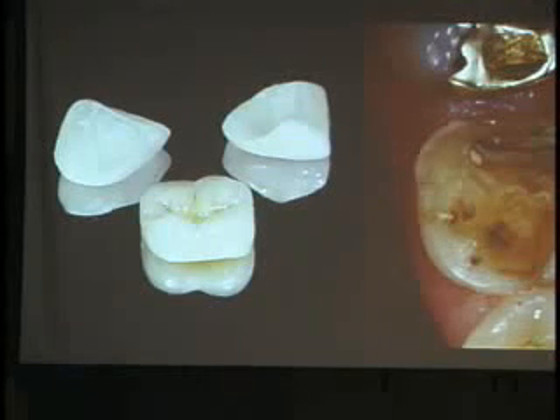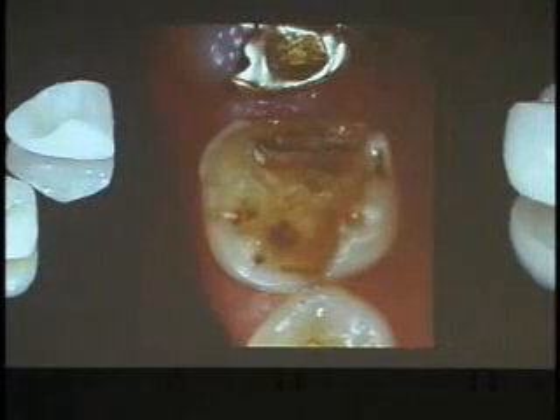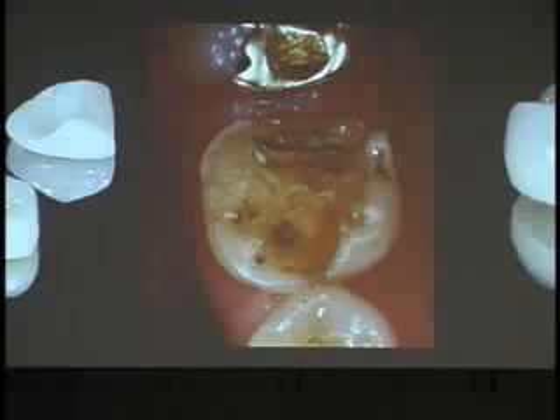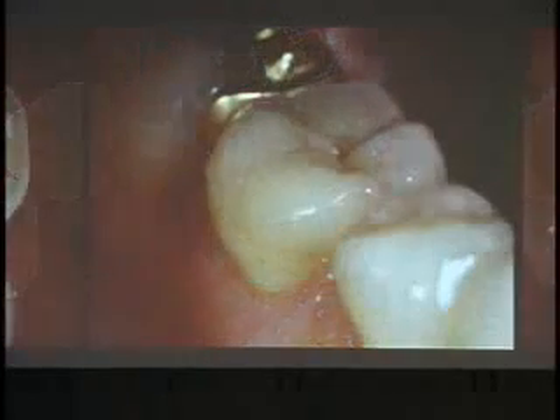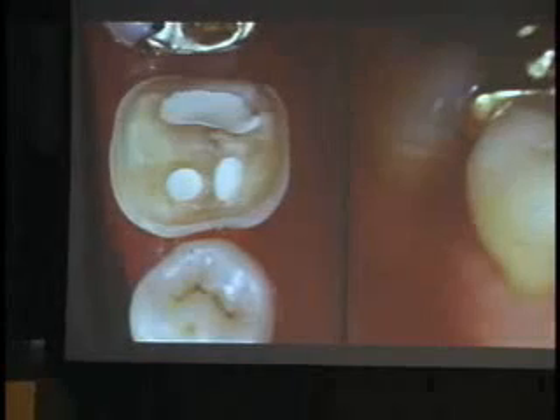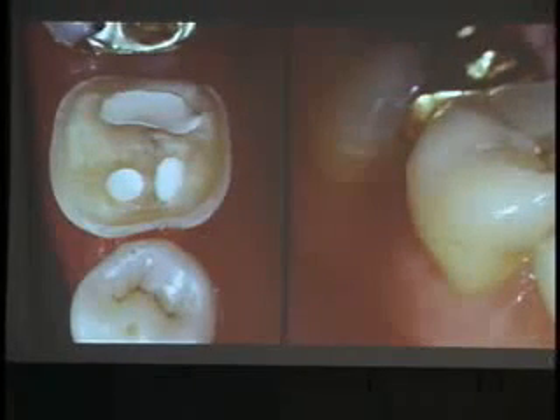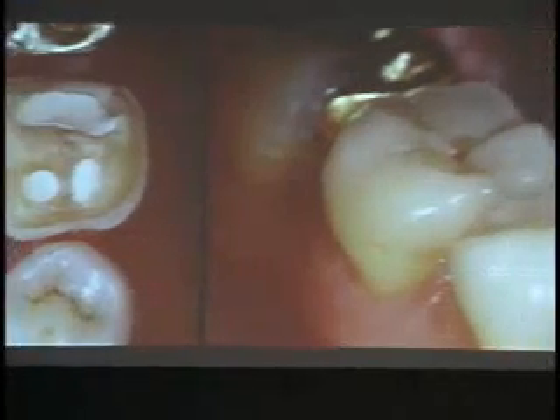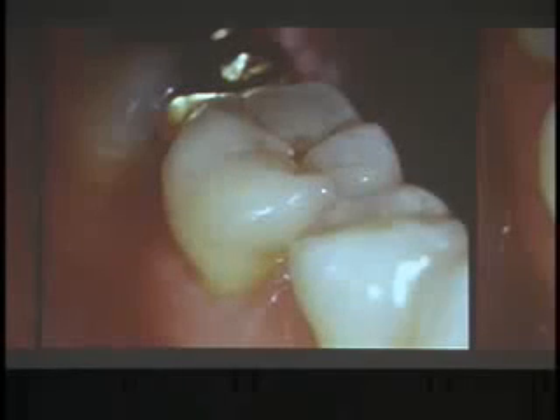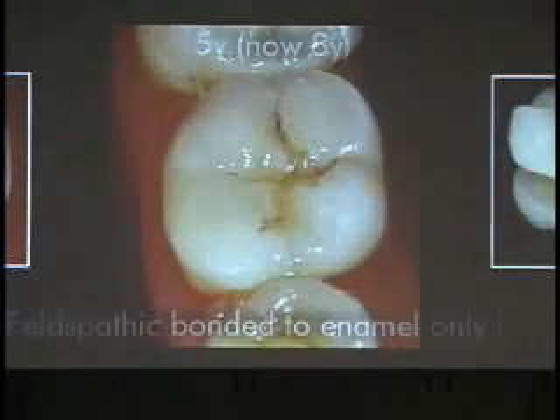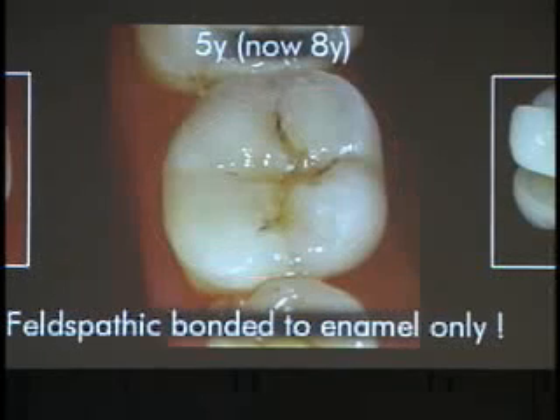I want to show you that example, which is an old case I did, again at a time where dentin bonding was not at all popular, and it didn't work. So I was using at that time sometimes copalite with calcium hydroxide, sometimes zinc phosphate. In that case, I had very little enamel left, but I used that just to bond my overlay, because I said, anyway, this tooth is so short, if I want to use a regular crown, I will need to devitalize, maybe do a build-up, a post, a core, and I don't want to do that. So we took this risk, and that was actually 8 years ago. This picture was taken at 5 years, but this restoration is still in the mouth today.